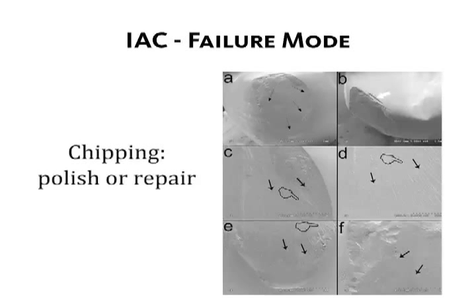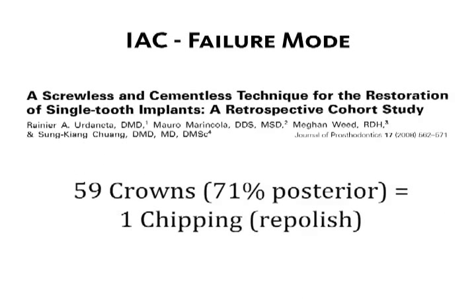Interestingly, failures occurring even at high loads comprised chippings that could be either polished or repaired, depending on their extent, as you may see from these scanning electron micrographs. This is exactly how they have been shown to fail in a clinical study where, out of 59 IACs, only one chipping was observed, which could be repolished and the crown returned to clinical function.